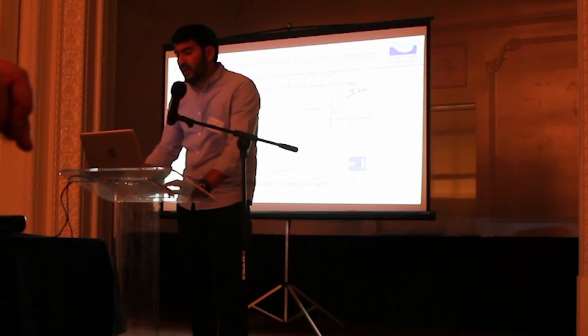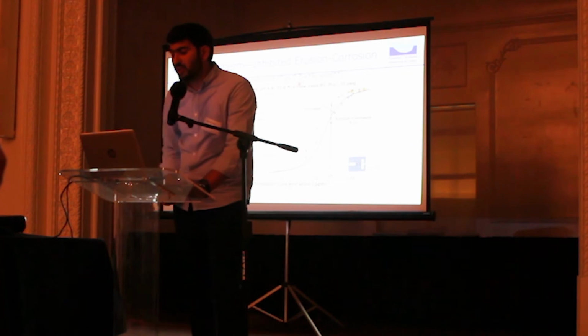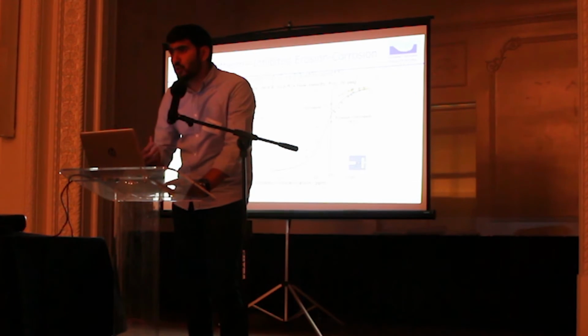Under the same environmental conditions that are discussed here, Hassani and co-workers at ECRC have conducted inhibited erosion corrosion experiments in a flow loop with a direct impingement configuration. The erosion corrosion experiments were conducted with 0.3% by weight sand concentration. And here we can see the inhibited erosion corrosion experimental data in this graph. The blue square data points represent inhibited erosion corrosion experimental data with 0.3% by weight sand concentration.